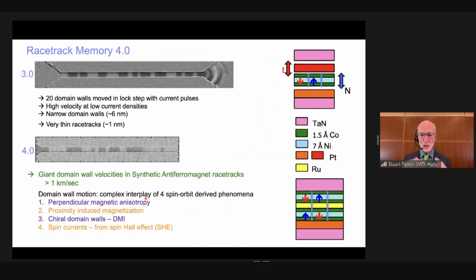And let me just show you, most of our physics, the physics to explore materials, is accomplished by using optical detection methods. So in the top of this slide, you can see a racetrack which is 3 microns wide, and the black and gray regions correspond to magnetic moment pointing out of the foil or into the foil, and the domain walls are in between these black and gray regions. We pass nanosecond long current pulses into the racetrack, and you can see all the domain walls moving together to the right and then to the left as we reverse the current direction in the pulses.